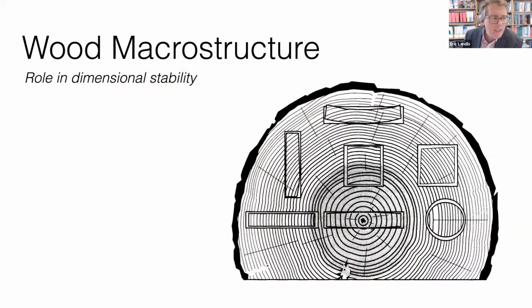Another element that's worth noting in wood macrostructure is the role of dimensional stability. So like concrete, but orders of magnitude more, wood shrinks and swells with changes in moisture content, but it does not shrink and swell the same in all directions. In the tangential direction, remember the tangential being along a growth ring, it shrinks at a higher strain rate than in the radial direction. And that difference is why we get some types of warping within a board. If you have a board with a cross section like this, you're likely to get cupping because of this differential shrinkage.